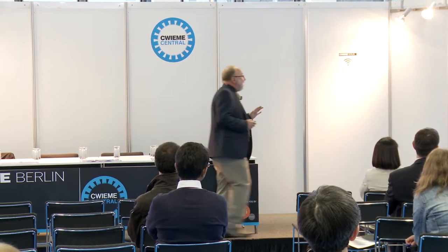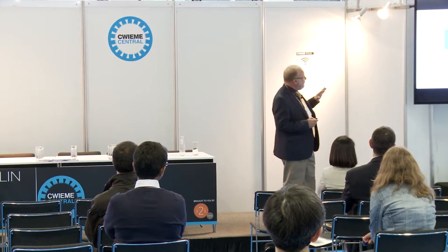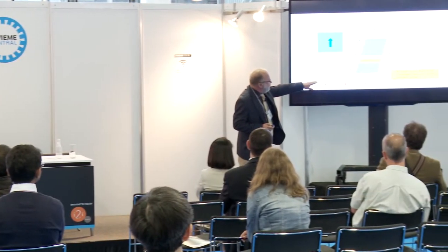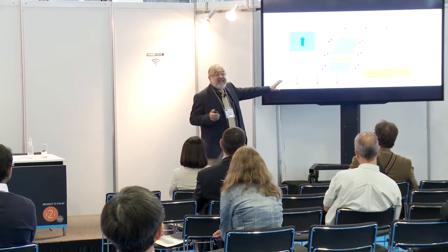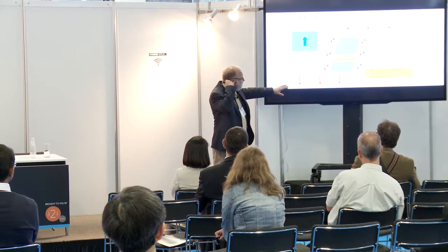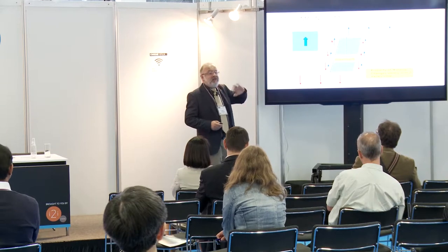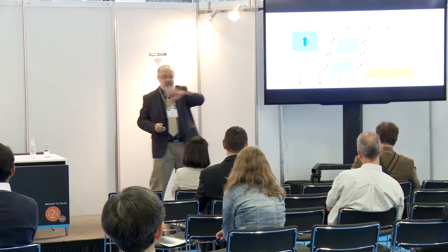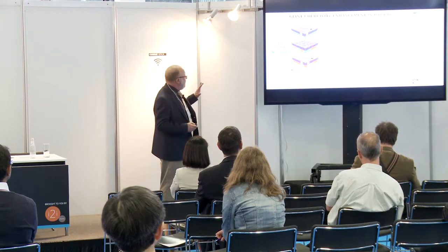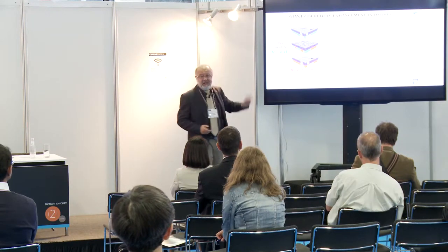And it turns out that if you do something very unusual, which is the following, you take pretty much any magnetic material. Now notice here, the coercivity is a property of the material. For instance, nickel has this coercivity. It changes slowly with temperature, and it varies very little over a temperature range.